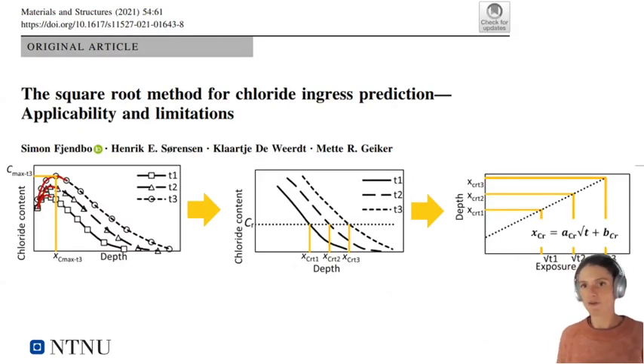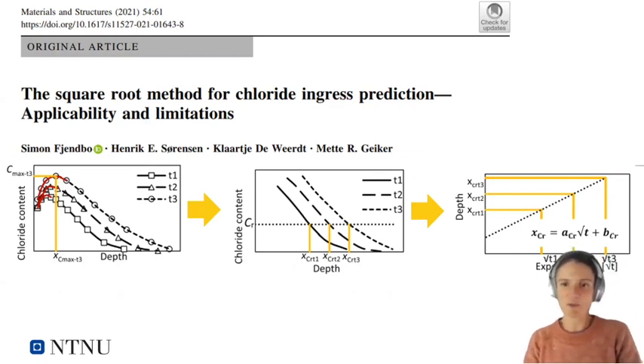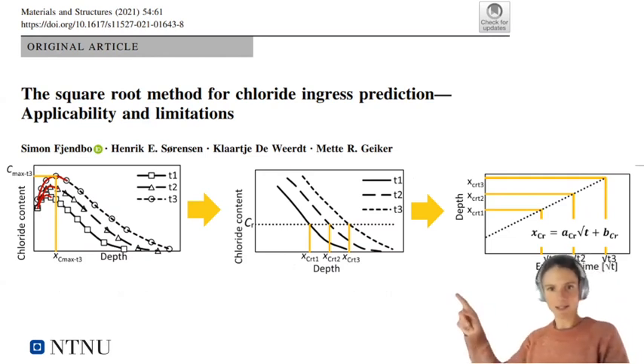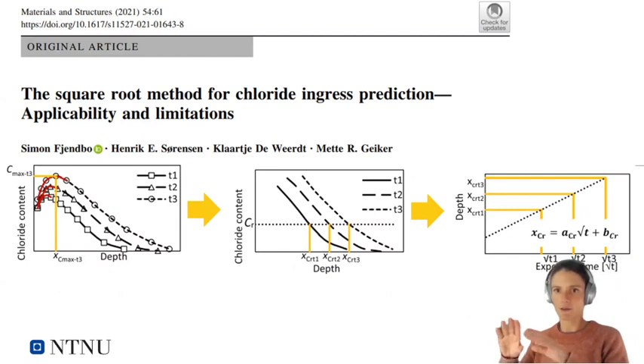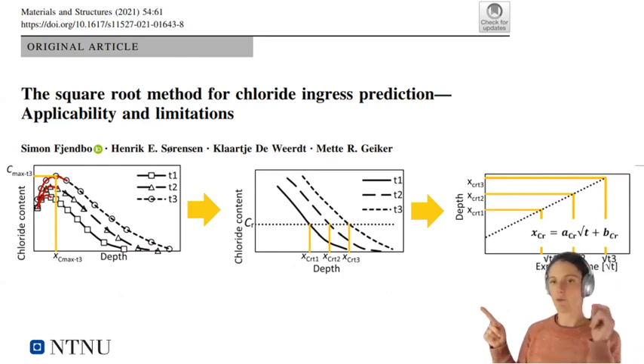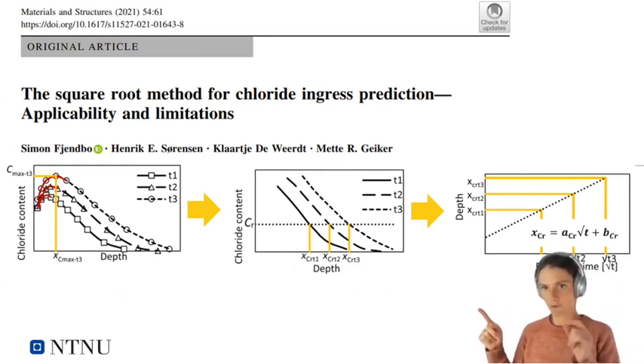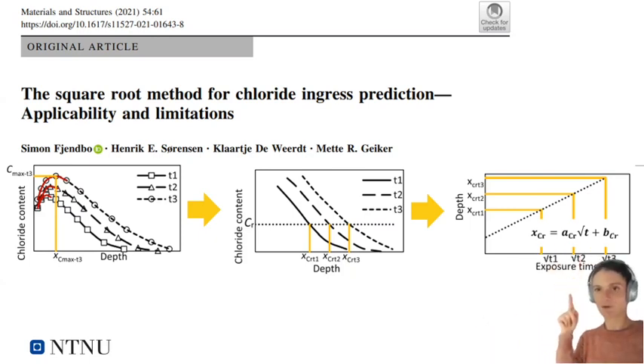So one example of how to deal with this is a model proposed by one of our former PhD students, Simon Fjendbo, and he looked into the square root method to look at chloride ingress predictions. And what he does there, as illustrated in this first figure, is he discards the first part of the chloride profile, which is heavily affected by leaching. And he looks deeper into the chloride profiles, defines, as shown here in the second figure, a reference chloride content, and he determines the ingress depth for that reference chloride content on the chloride profile. And then he determines this depth for different exposure times. And when you then plot the ingress depth as a function of the square root of the exposure time, you get a linear function. So this is a very simple engineering model to predict chloride ingress over time.